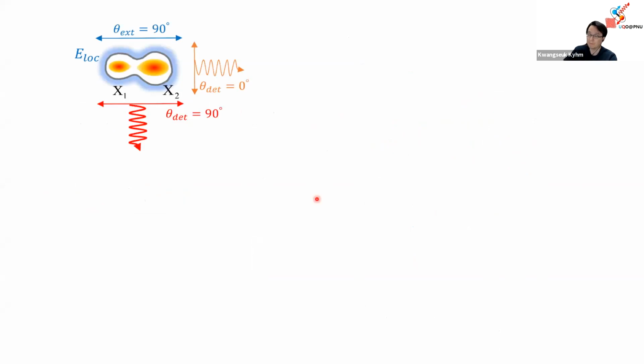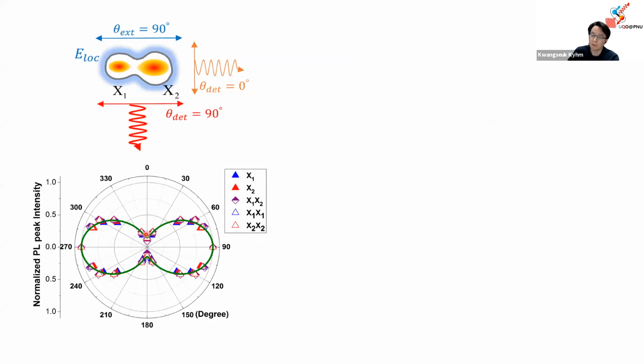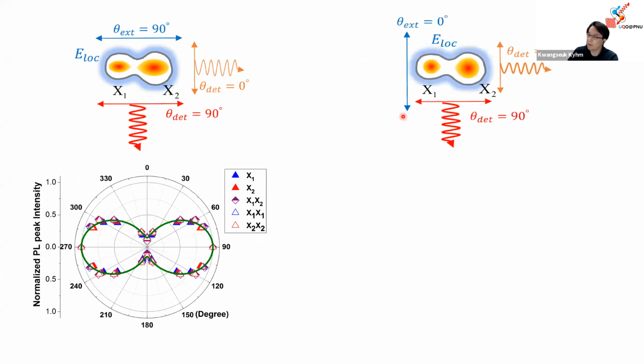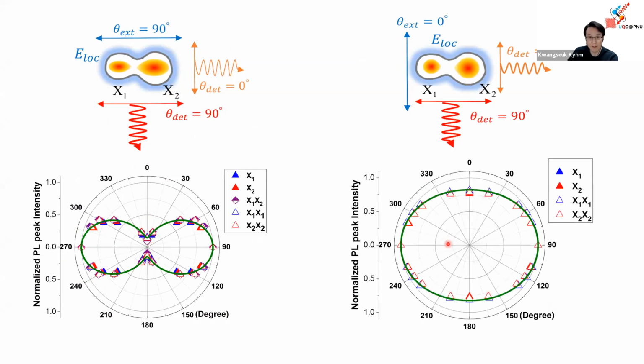Okay. And now we analyzed the emission polarization by using a linear analyzer. So the definition of the angle is like that. This is 90 degrees for excitation. And for detection, this is 0 and 90 degrees. Okay, so that's the result. Very anisotropic. So 90 degrees, here 0. On the other hand, with 0 excitation, the anisotropy is different. So although it's a non-resonant excitation, a different anisotropy is obtained. That means the wave function shape will be different.